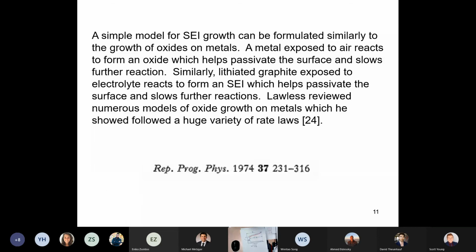You see it in the electrolyte reduction curves of cells. If you see a peak altogether due to the additive that then eliminates the EC reduction peak, you say that additive has controlled the SEI formation, right? There would be no LEDC at all. Yeah, but anyway, just to go back to Aniko's question, it really was a question of why do we pick these three? Because they don't react, they work well.